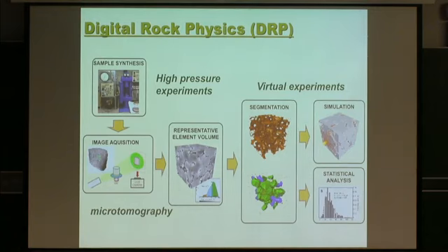That is because the melt, basaltic melt especially, and the olivine, if you just look at their density contrast, it's not that much, so a lot of the time the resolution is not that high. So after that, once you get the image, you select a representative volume and segment melt from its solid, and then you essentially have a digital rock that has a representative 3D microstructure.